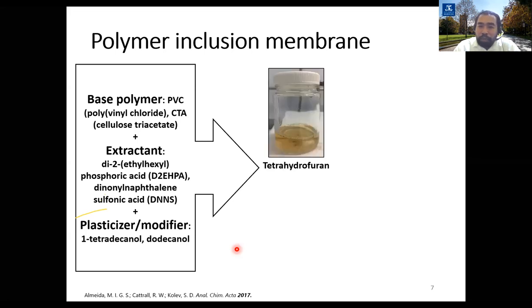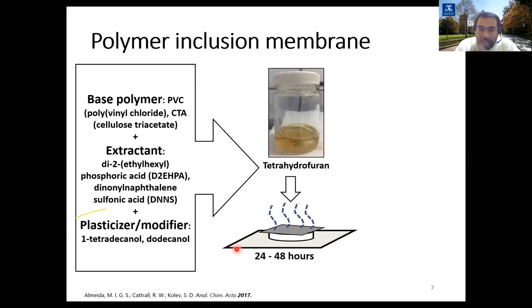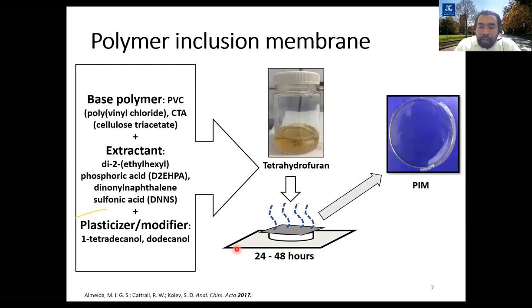The way we fabricate the polymer inclusion membrane is very simple. Basically, we mix all the components together in a suitable solvent until all of the components are completely dissolved. And then we pour the super clear solution into a glass ring, which is positioned to sit on top of a glass plate. We then cover this glass ring with filter paper to slow down the evaporation, which then results in a very homogeneous, transparent and thin polymer inclusion membrane over 24 to 48 hours.